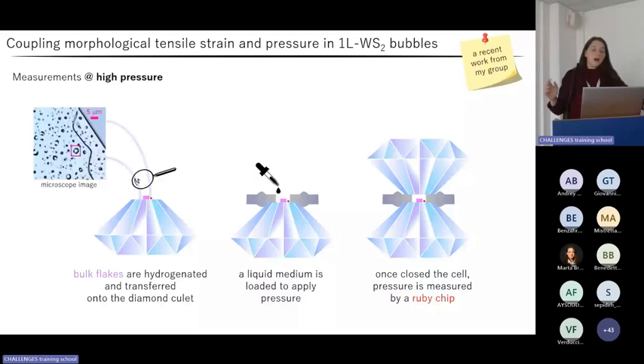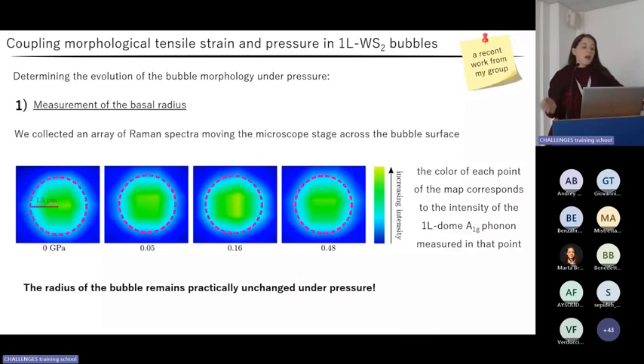In order to perform high-pressure measurements on these samples, we transferred a pre-hydrogenated bulk flake with the bubbles on top onto the culet of our diamond anvil cell. And then we loaded our measurement chamber with a liquid pressure transmitting medium in order to apply a nearly quasi-hydrostatic pressure on the dome. Once identified a bubble of interest, at each pressure, we collected a two-dimensional array of Raman measurements, mapping the whole bubble surface.